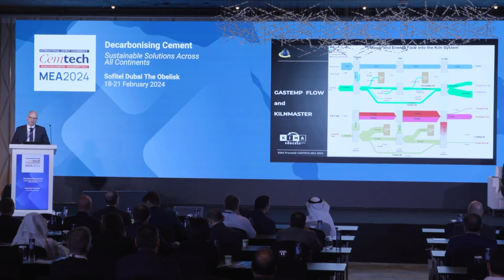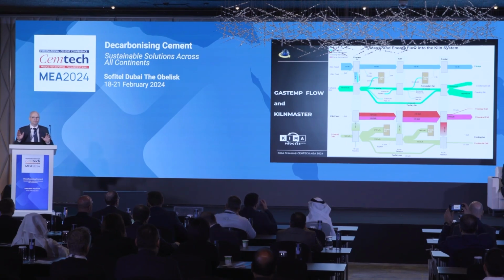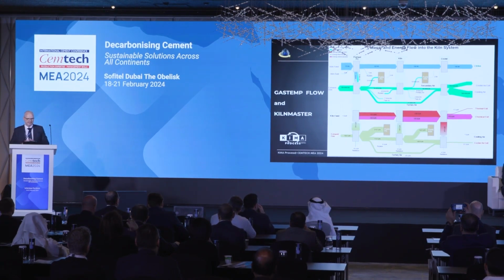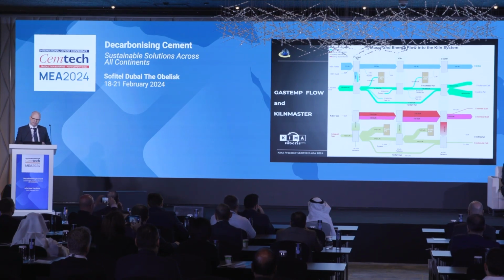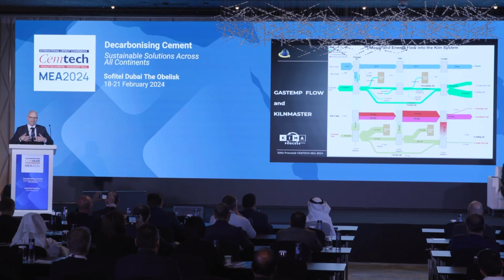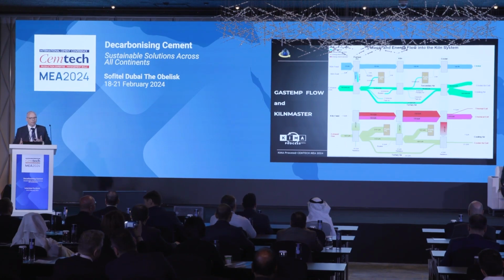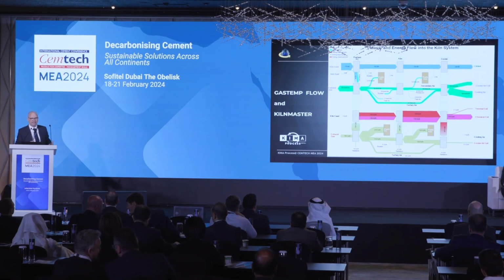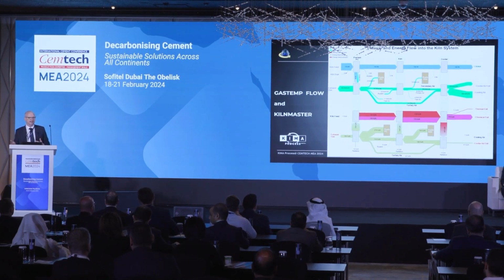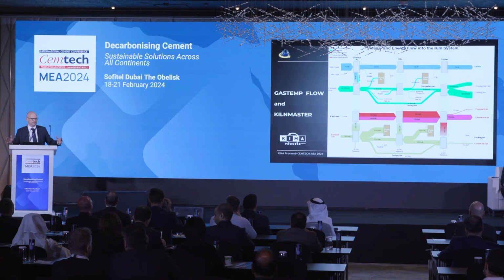I come to this a little bit later. Now, when you measure the gas flows and the process so precisely, you can see immediately when there is, for instance, a change in the heat value of your fuels. If you start with alternative fuels, you need information on where the change in the heating is, where the change in the energy input is, and which effect this has on the entire process, to avoid the scaling effects.